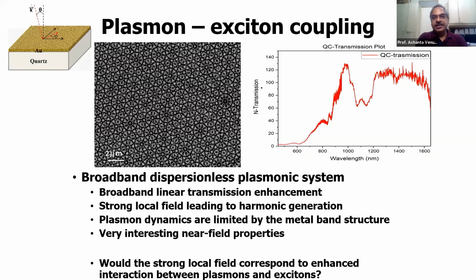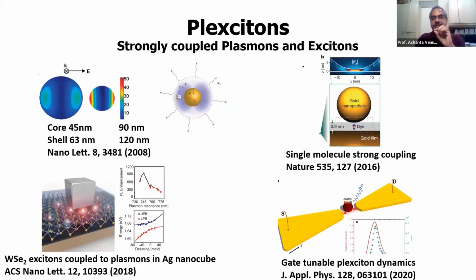Once you have this quasi-periodic structure, we showed about 120, 130 times enhancement in the transmission of light through this. You shine light from here and measure the transmitted intensity and compare it with the unpatterned gold metal transmission. Compared to that, you get about 130 times enhancement in the transmission at the peak. What it means is you have very strong plasmon excitation, so you have a very strong local electric field.